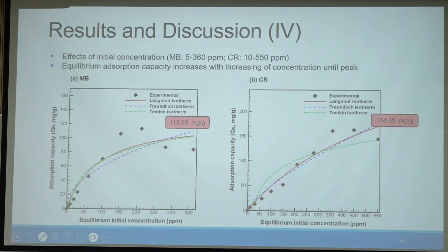So this is the model that tracks the absorbent capacity that we are following. For this study, we use 3 isotherms. One is Langmuir, and the other two are Freundlich and Temkin. We see which one has the curve closer to our absorbent capacity.